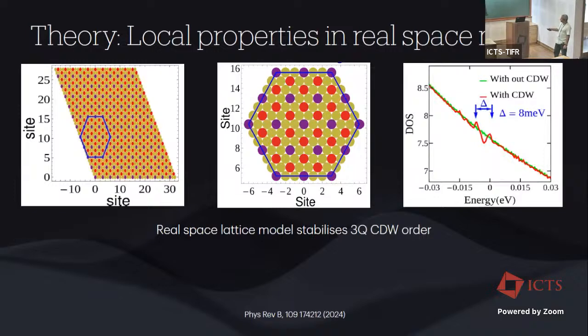state nicely. And if you look at the density of states, which is averaging the density of states over the entire lattice, you get a peak happening around the same point you see in the experiment, a dip feature, which is not a complete dip, representing a very anisotropic CDW formation.